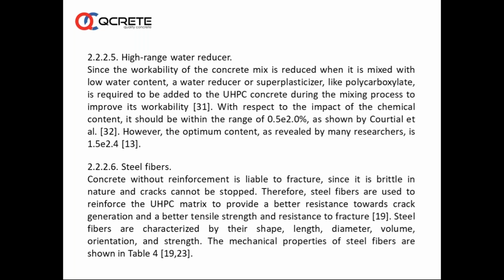The reduction of water cement ratio to 0.14 or 0.22 is possible only because of such extraordinary water reducing capabilities of polycarboxylate ether based materials or polycarboxylates.